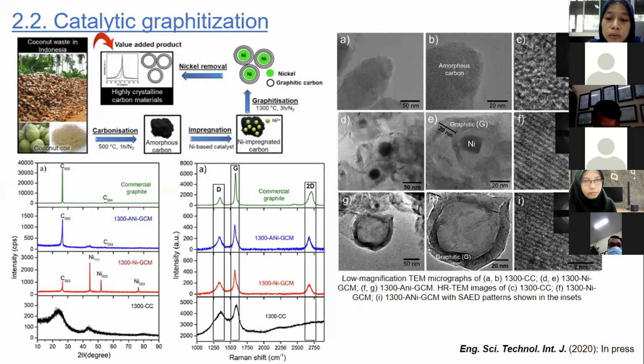as 1,300 degrees Celsius. The TEM image of the sample without catalyst was typical of an amorphous carbon material. The diffuse halo in the SAED pattern confirmed that the carbon without catalyst was an amorphous phase, while the nickel treated sample indicates the presence of graphitic structure obtained at the same temperature with catalyst.